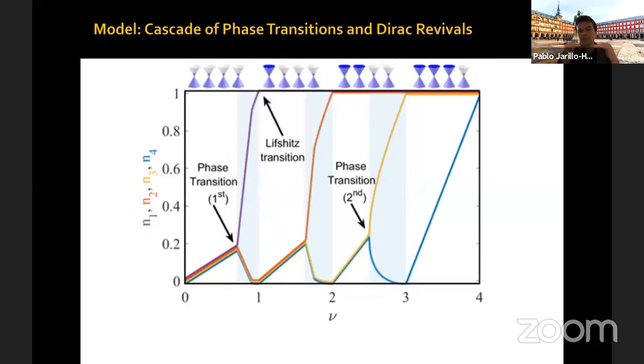And the way we interpret this is the following. At charge neutrality, you have these 4 Dirac cones coming from the K and K prime valleys and spin up and spin down. So you have these 4 flavors, which are, in the simplest approximation, degenerate. So as you start filling these flavors with charge, all 4 flavors fill at the same time. Now, close to but before 1 electron per moiré unit cell, so when you're close to filling 1/4 of each of these flavors, 1/4 each means 1 electron per moiré unit cell because we have 4 flavors, then a phase transition happens, where the system suddenly decides, due to Coulomb interactions, it's energetically more favorable to occupy a single flavor. So the charge goes to 1 flavor and the rest of the flavors get emptied. So they go back to charge neutrality and then the process starts again.